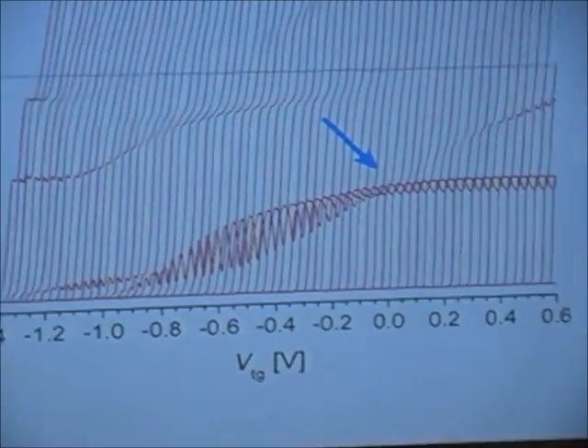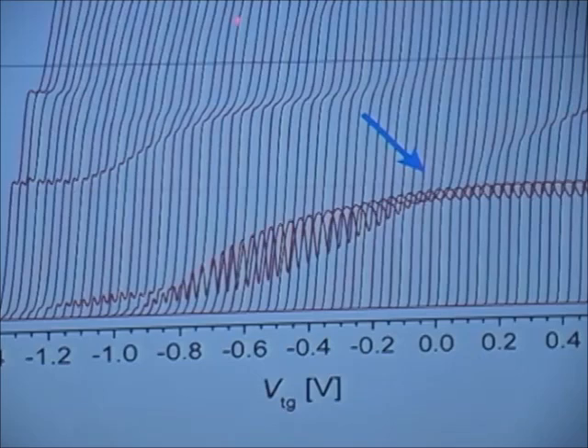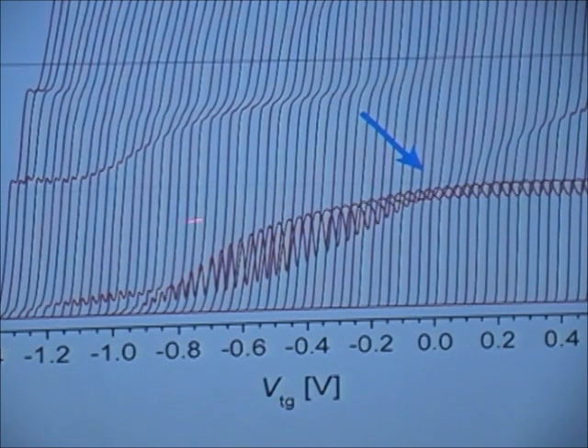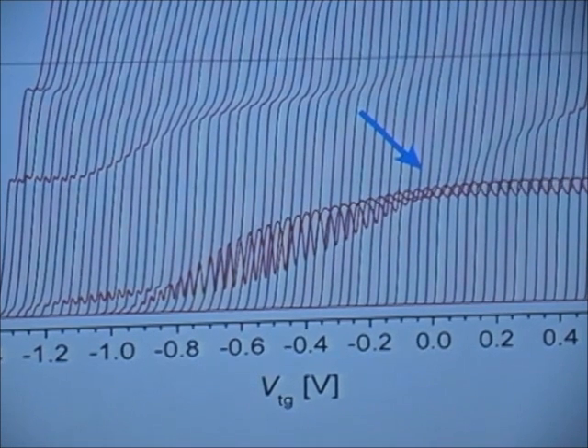What this actually is, is an example of what happens when two different states become close in energy. They're moving down because we're allowing the electron gas to spread itself out. We're giving it flexibility in that extra dimension. So it doesn't know what is the lowest energy. It can be the conventional subband picture, which we've discussed before, or it could be the direct formation of 2 rows. What happens is it tries to form 2 rows immediately, goes into that, and then energetically it becomes more favorable to go to the conventional subband picture, and the conductance drops and then rises. And the overall envelope shape is actually like a beat. But I don't want to go into that in detail because it gets rather complex. But to give an example of the manipulation of the electron gas which can be achieved in this way, the electrons and the wave functions can be modified almost according to what one wishes. And it gives rise to a host of new types of physical phenomena and effects.